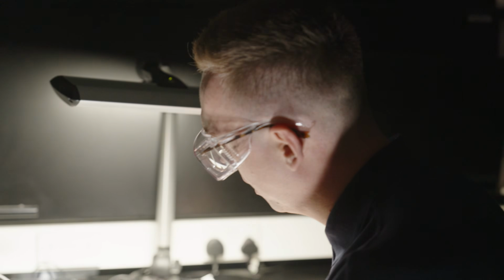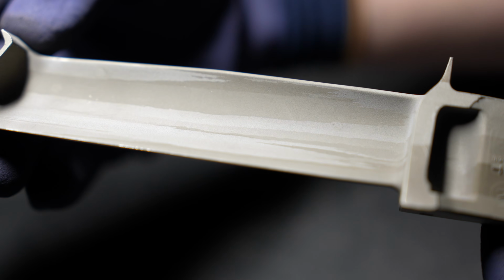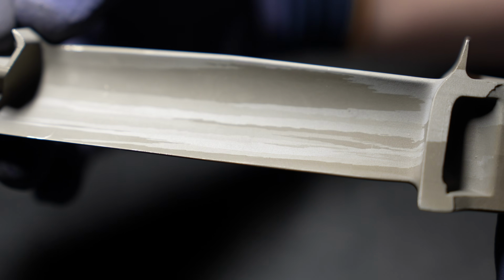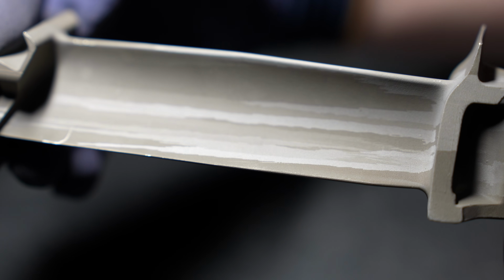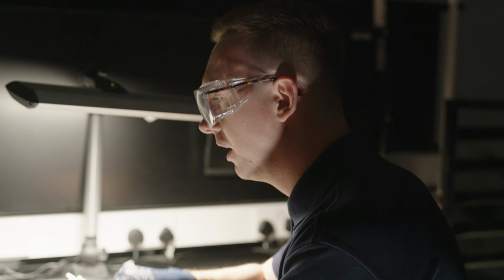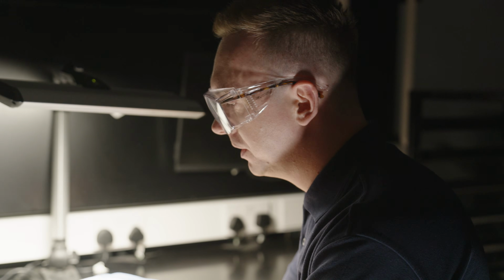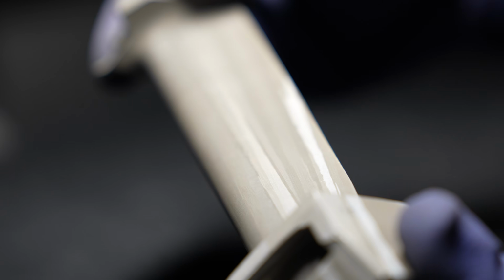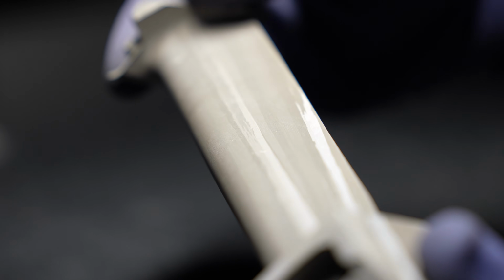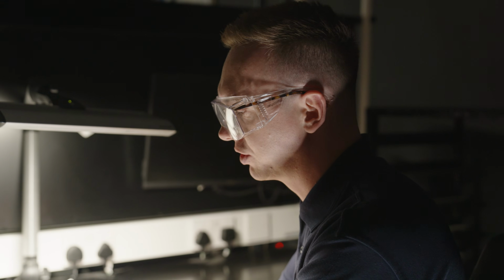Now, if we just did that on its own, you'd end up with a blade that looks like this. Here's a directionally solidified blade, and what you can probably see there is the contrast between the grains. These are all different crystals, but they're all running on this axis of the blade, which makes it significantly stronger than an alloy that is cast, where all of the crystals are separate from each other. So those are like individual crystals? These are individual crystals, yeah, absolutely.